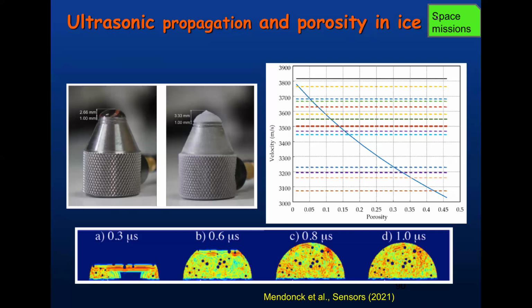And we used a model from this group so that, for a given experiment, we can see what the porosity level is. So this is 10% corresponding to each ice. It's something we wanted to try. We haven't done it in the vacuum chamber, but in principle, you can do it. The challenge is that you are working with ultrasound in vacuum, but it works. If you get enough money to do it, you can do it. And this is quite breaking results.